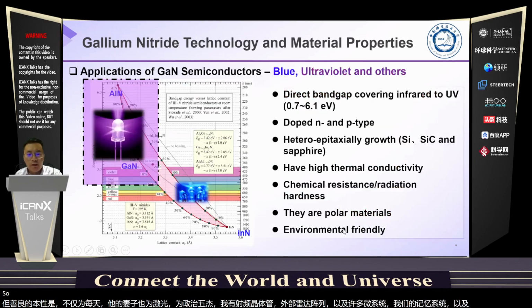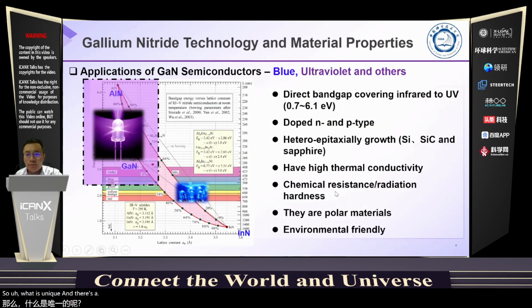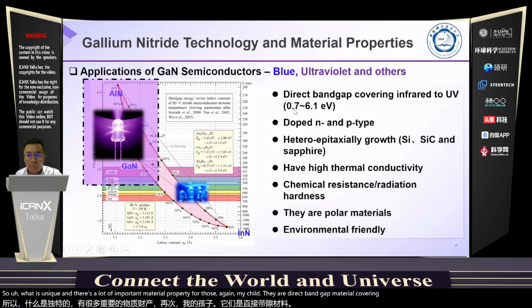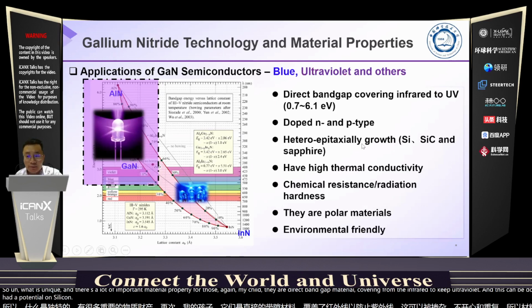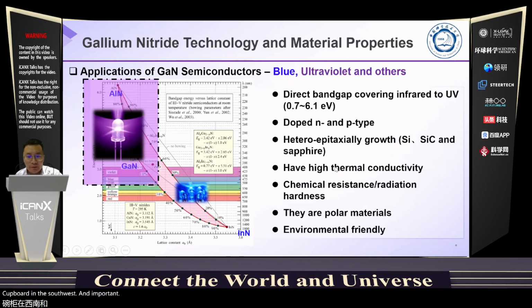So what is unique, and there are a lot of important material properties for gallium nitride. They are direct bandgap materials covering from the infrared to deep ultraviolet, and can be doped N-type and P-type. The material can also be grown heteroepitaxially on silicon carbide and sapphire. And importantly, they have high thermal conductivity, and most importantly, very strong chemical resilience.